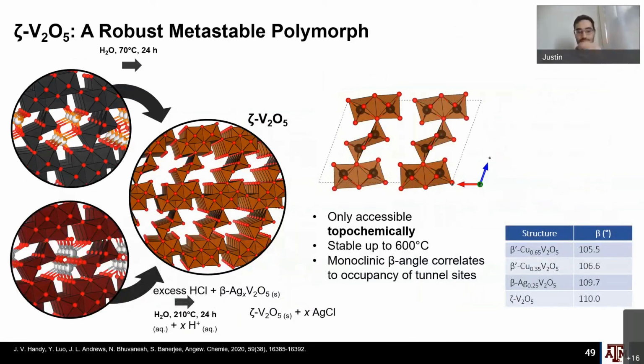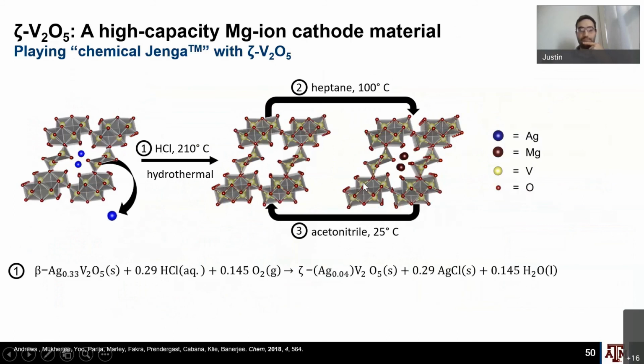And just to take a step back, this should have come first, but for those more interested in the synthetic aspect of this, the way that we do this is we intercalate, for example, silver or copper into the structure of V2O5 to rearrange it, and then we can etch this out with acid to form these one-dimensional structures. This is a nice close-up view of that.